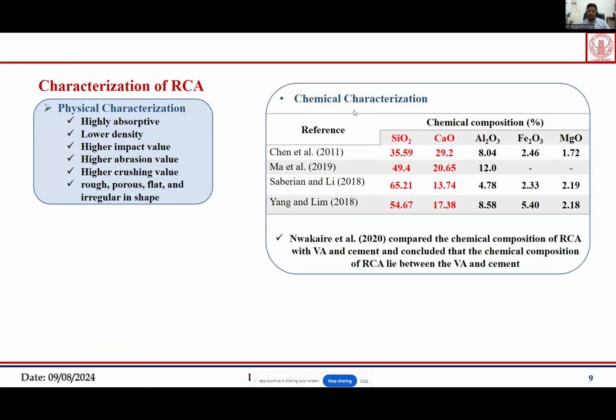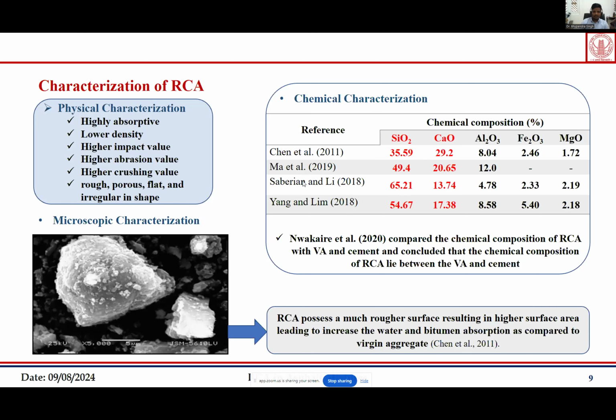If we see the chemical characterization, you will find that SiO2 content is really high in these recycled concrete aggregates, which is a problem from the asphalt mixture point of view, because we have seen that aggregates which have higher SiO2 content are poor in making bond with the asphalt binder. So that is the problem. Coming to the microscopic characterization, you will see that the surface of RCA is much rougher as compared to natural aggregates. So these are the characterization of RCA.